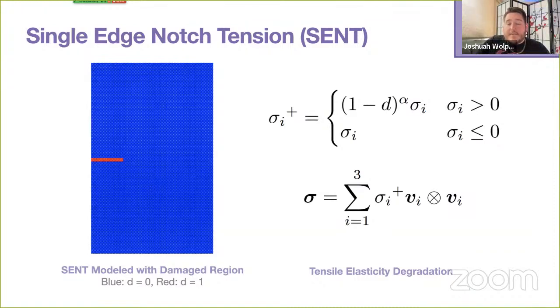So this elastodamage coupling simply uses the particle damage D to degrade the tensile portions of the material stress, meaning that fully damaged particles should be able to physically separate under tension. Then one of the simplest validation tests we can do on this specimen is simply to measure the traction at the crack surface. In particular, because we're loading this crack with tension up and down, the crack surface on the top and bottom should be traction-free, showing nearly zero stress in the up and down directions.